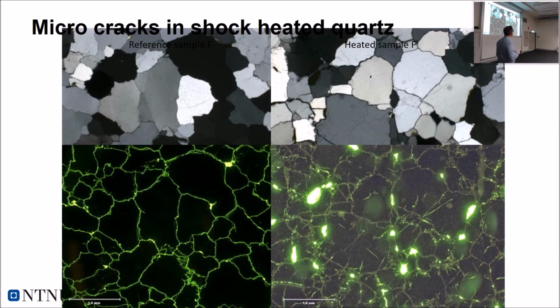We've also seen this as an indication of cristobalite formation. So those of you that know the phase diagram for silica, you know that quartz is a natural ambient mineral. When you heat it up to different temperatures, you have transition to beta quartz and later to cristobalite. And when you have formation of cristobalite, which we'll look into afterwards, quartz expands about 15%. That's a significant expansion that contributes to this internal cracking and deformation.